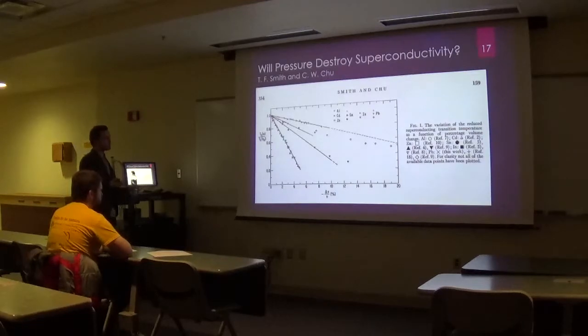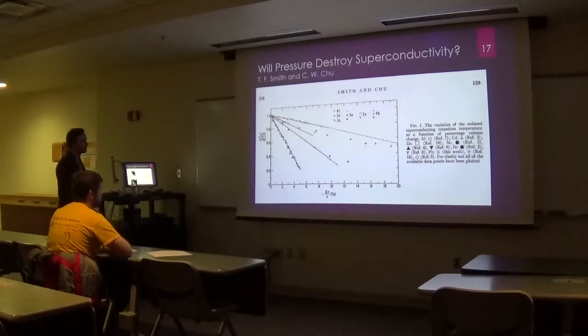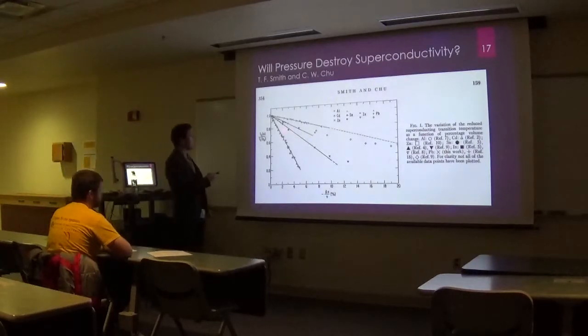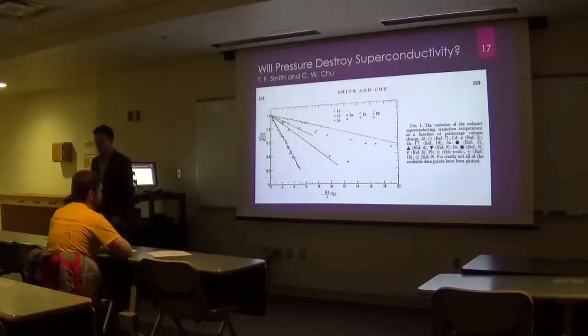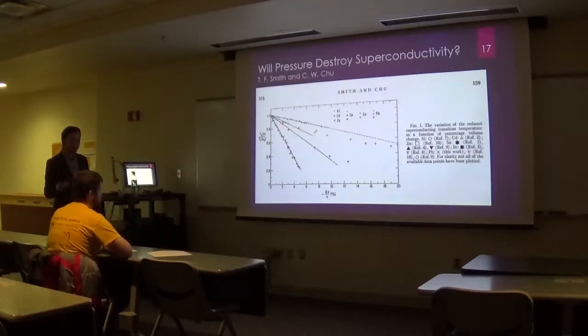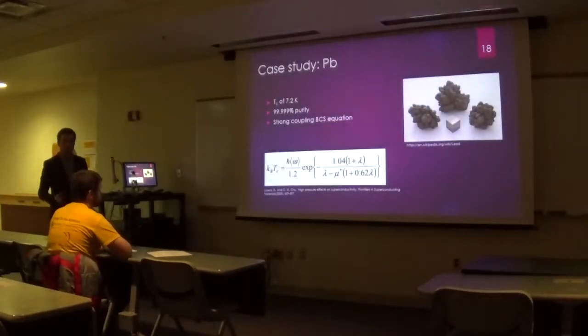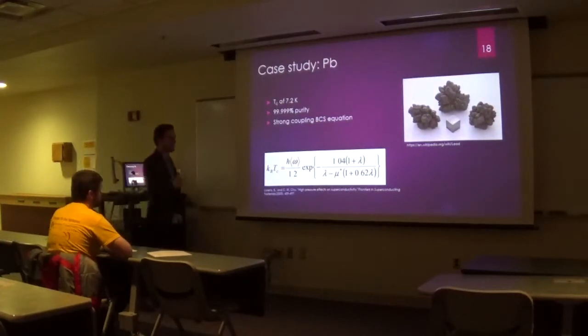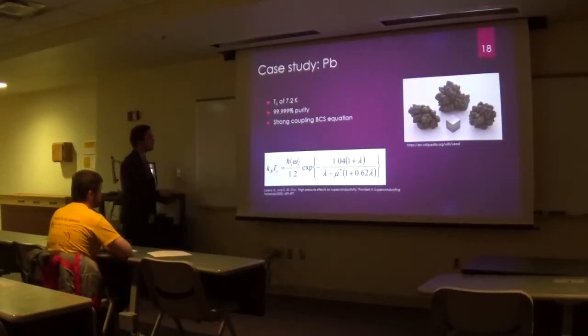The goal of it was to see at what pressure we could completely suppress our superconducting phase transition, effectively making our critical temperature zero. So what they say is, if we assume that these relationships between our critical temperature and pressure keep on going when we increase our pressure, then yes, we can eventually completely suppress our superconducting state. So we want to figure out what is exactly happening.